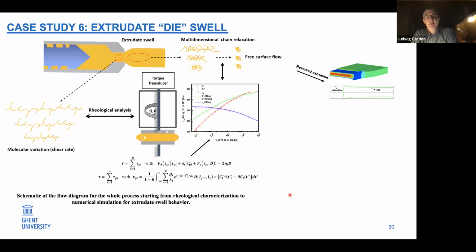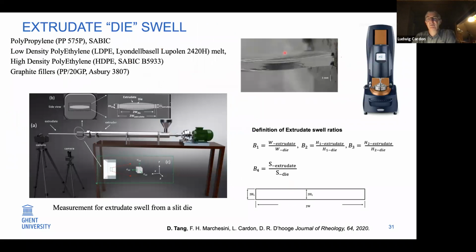So another aspect in the flow behavior we investigate is the so-called die swell. I mentioned that very briefly before in the scope of 3D printing, but in this case, we investigate that also in the scope of a standard extruder. What we did, and I think it's in the next slide, I pass by somewhat faster. We developed a system with two cameras. These are high-speed cameras, which we combine with video capturing. So we capture the processing itself of the polymer. We measure the variation of the die swell when it occurs.